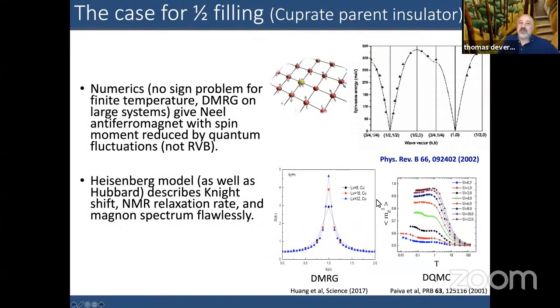So going back to the case for the cuprates, if we stick at half filling, the antiferromagnetic insulator, numerics does a really good job of nailing this problem. We have no sign problem at finite temperatures. And so that enables us to really explore the nature of the high temperature to low temperature evolution of the states, as well as the dynamics. And the bottom line is that this is really well described by Heisenberg-like models. That's a Néel antiferromagnet with spin moment that's reduced by quantum fluctuations, but not like RVB.